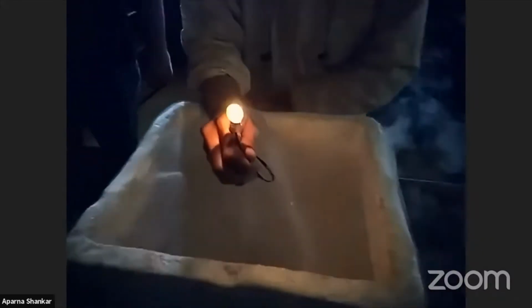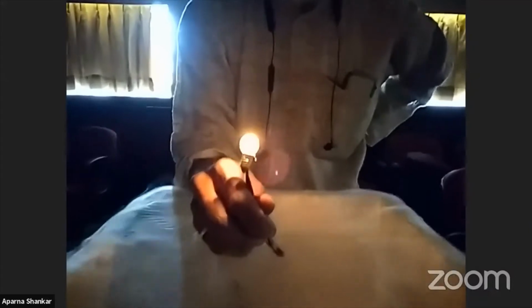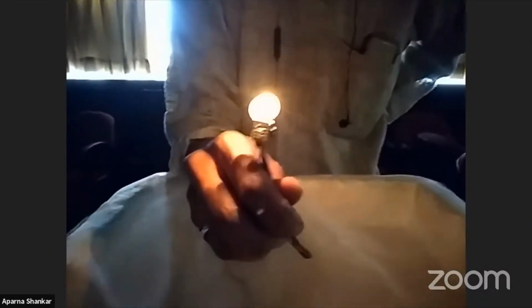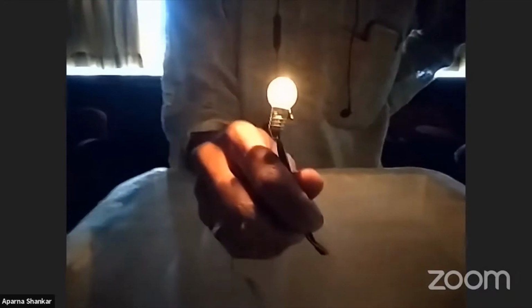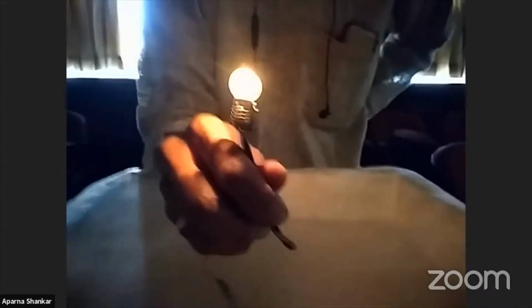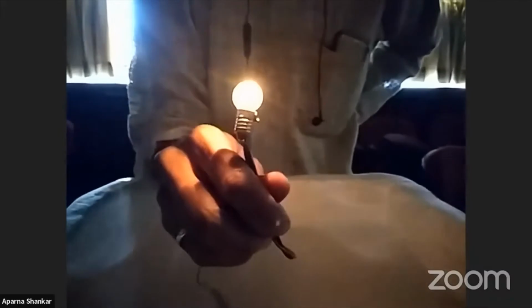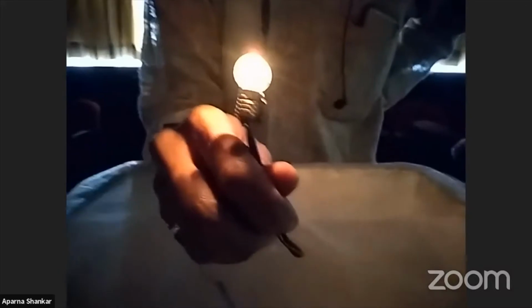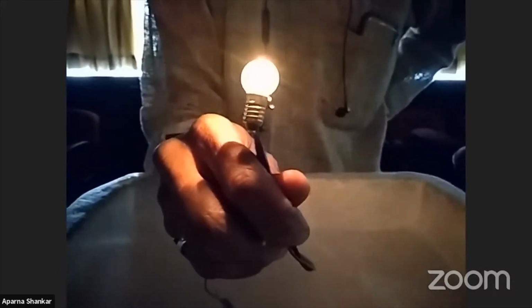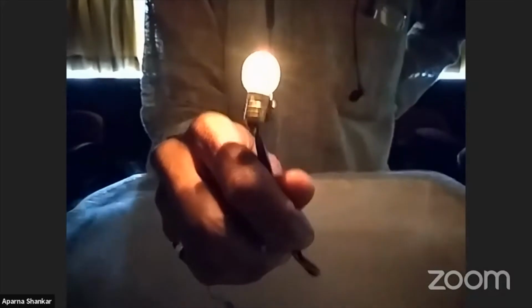Now I'm going to cool this coil and put it in the liquid nitrogen and see what happens to the bulb. Slowly the resistance of the copper wire is reducing, and you can see the bulb has started glowing brighter now. Can you see the intensity going up? So the amount of current flowing through the copper wire has increased, and it has gone up in brightness. If I remove the coil from the liquid nitrogen, it will come back to room temperature, and the resistance will automatically go up.